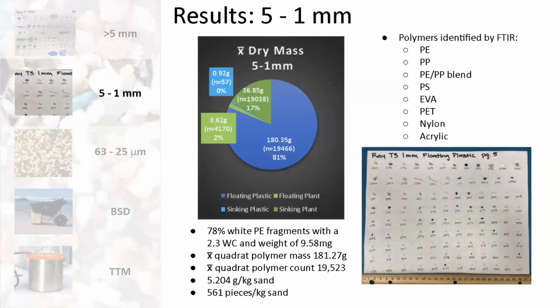For 5 to 1 millimeter, again, notice the mass difference, the particle difference, how much more abundant there was in degrees of microplastics compared to the larger plastics. 78% of them, again, white polyethylene fragments with a 2.3 weathering code and average weight of 9.58 milligrams. Our average quadrant counts. This is, again, a big one.